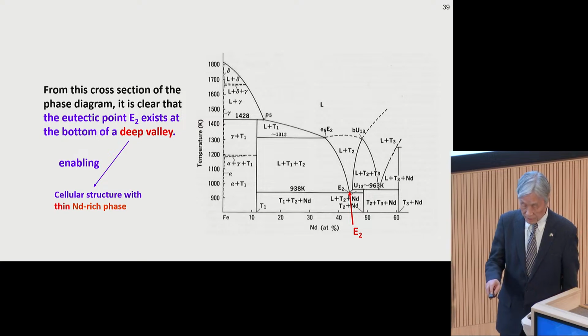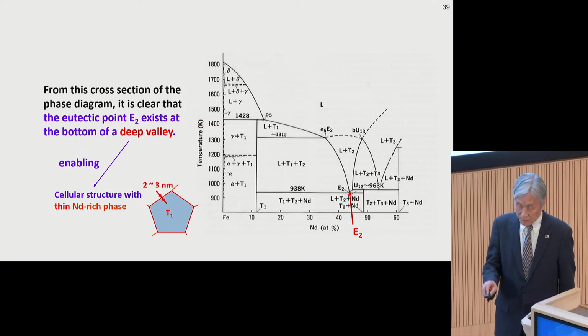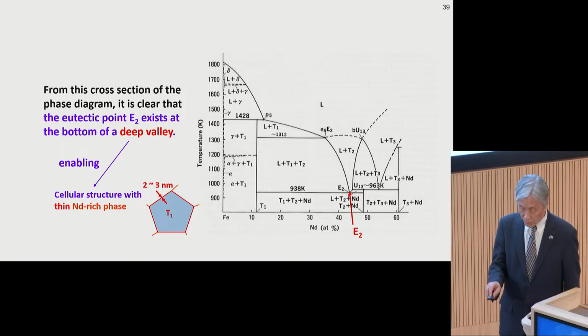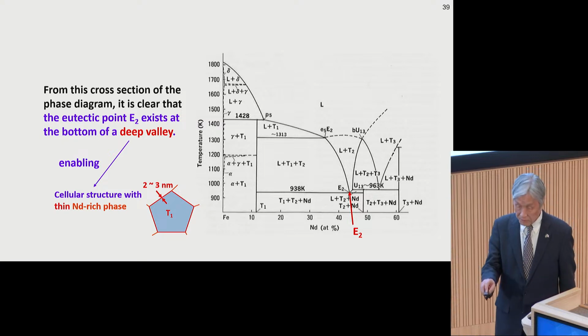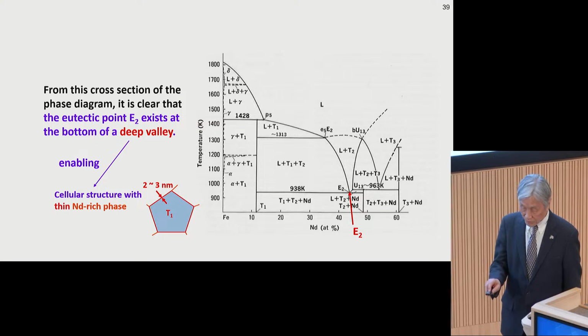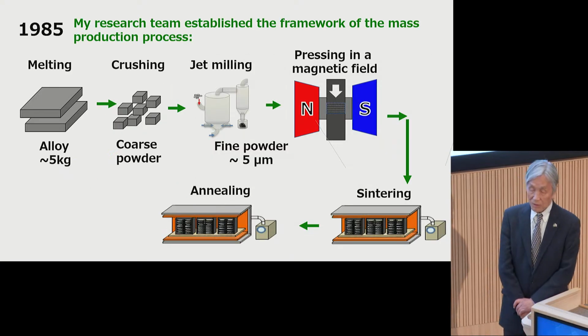And this, as I mentioned, enables a cellular structure with the neodymium-rich phase of 2 to 3 nanometers, very thin. This is important to get a high coercivity. And what is important is the neodymium-rich phase. The boundary phase is almost non-magnetic. This is also important. So we have very good magnetic properties with the neodymium boron system.